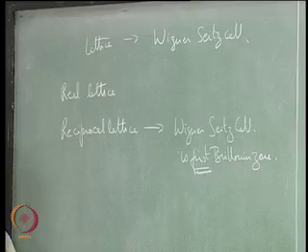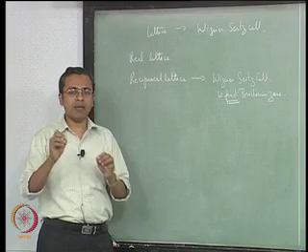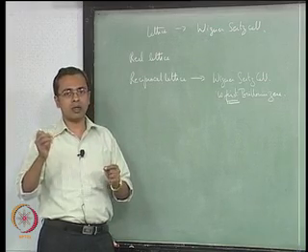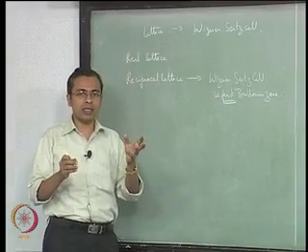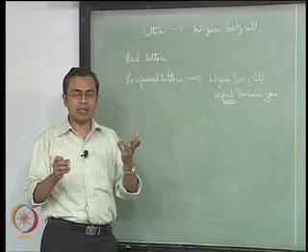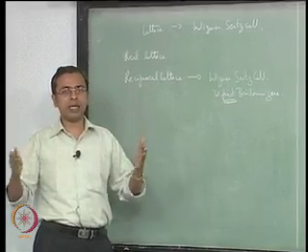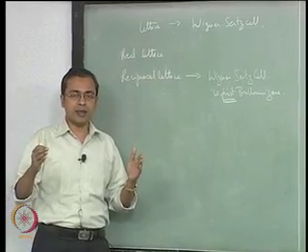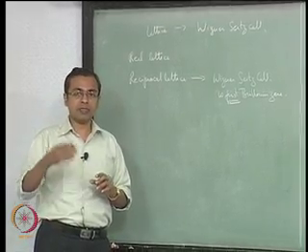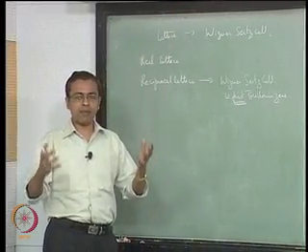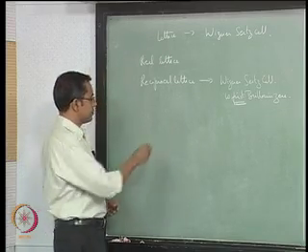Instead of talking of lines we have planes, and all those planes intersect along lines, and so the shapes that we identify begin to look complicated. Okay. So I have been able to show you the first Brillouin zone rather clearly. If you look at the second and third Brillouin zones in 3D, it looks rather complicated, but the process is exactly the same. You simply keep identifying planes that bisect the reciprocal lattice vectors to further and further neighbors, and then you keep identifying the structures where you cross only one Bragg plane and no further Bragg planes.